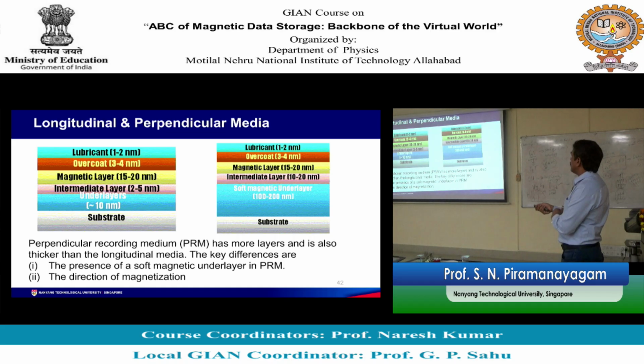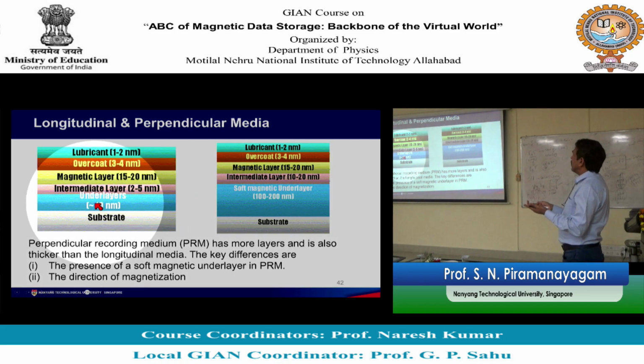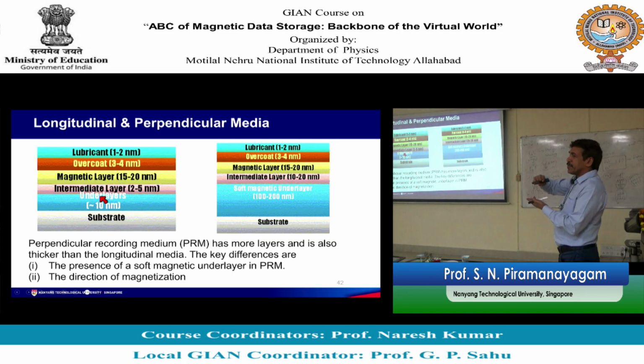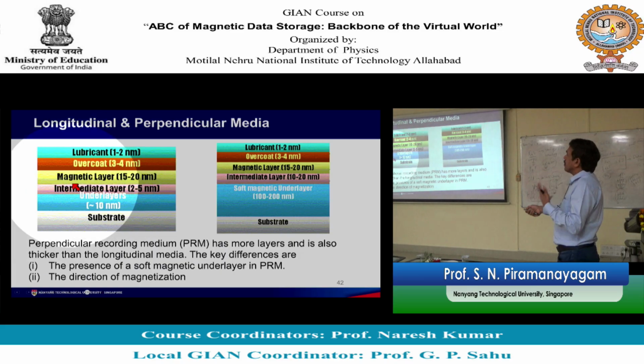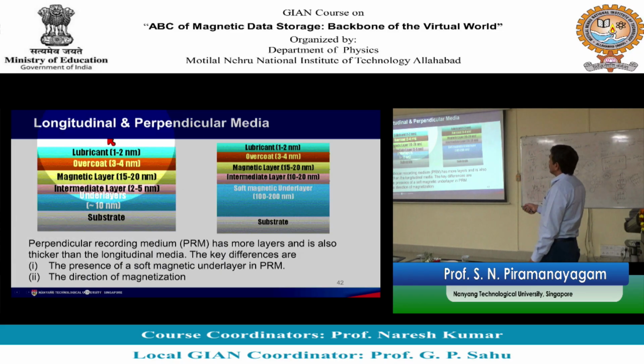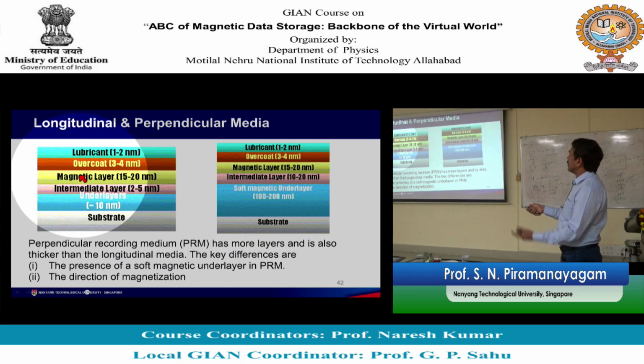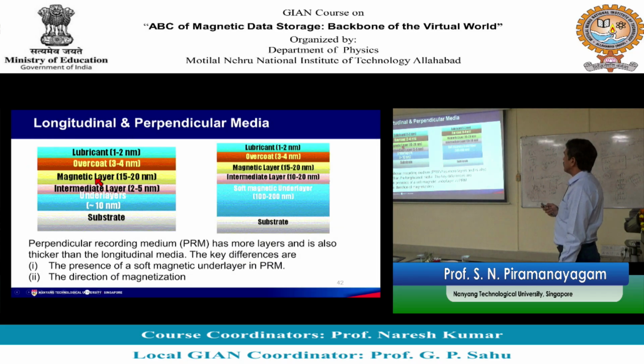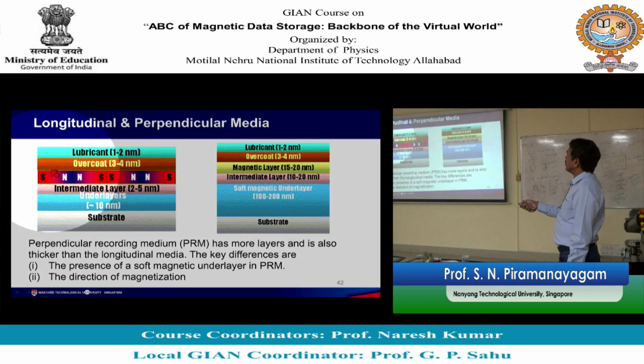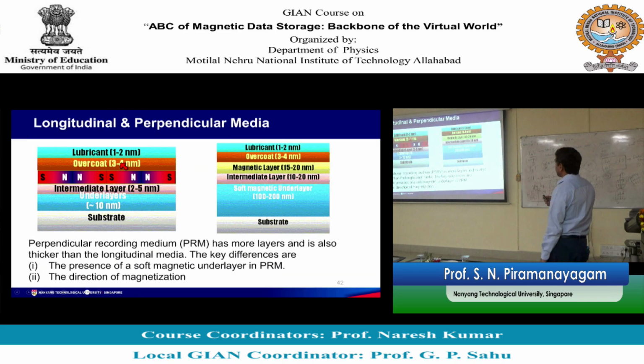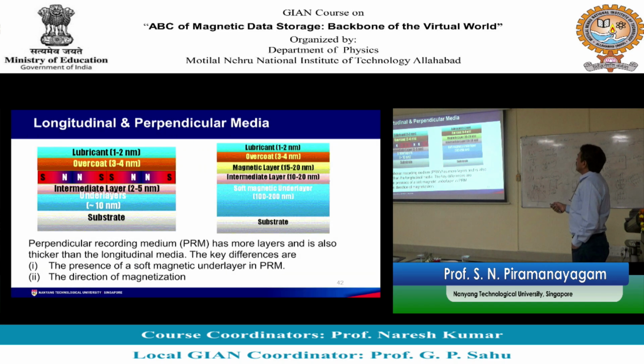So in the longitudinal recording, I told you we have some underlayers. The chromium layer helps to keep the magnetization of the cobalt in plane and so on. So we have a few layers. Now it's not always one layer. We have several layers, and out of which at least one of them is a magnetic layer that stores the information. And in longitudinal, you learnt that the magnetic poles are parallel to the disk surface. Okay, in perpendicular recording, you have a magnetic layer and the magnetization is now perpendicular. So the north pole, south poles are now perpendicular to the disk surface.